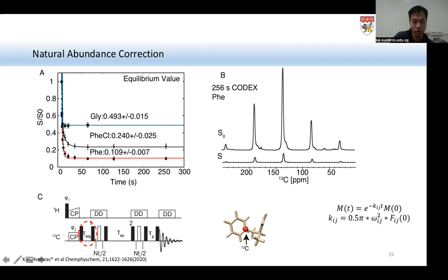This is actually because although our sample is isotope enriched, on the other sites 13C is not depleted. It has natural abundance, approximately 1%. And since we have 8 natural abundance spins nearby, these natural abundance spins contribute to the decay. It has an error range of 1% times 8, approximately 0.08. This is not a big problem to differentiate if the Z prime value is 4 or 3, but when it comes to 8, 9, 10, when we see plateau values of 0.125, 0.111, and 0.10, it will be confusing.